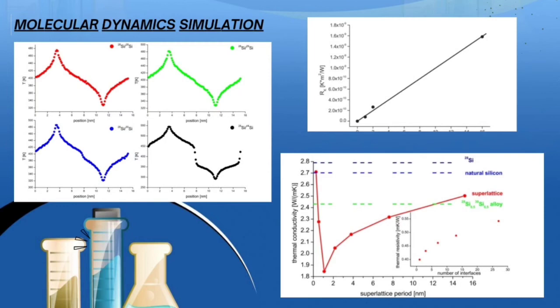Next, the graph shows the straight line of Kapitza resistance calculated for the isotope layer structure shown in the figure as a function of the mass difference of the silicon atoms on the right and left side of the interface. The last graph illustrates an increase of the thermal resistivity with increasing number of interfaces for superlattice periods equal to and greater than 1.09 nm. A linear increase is expected in case the thermal conductivity of the isotope superlattice is mainly given by a serial connection of the interface resistance.